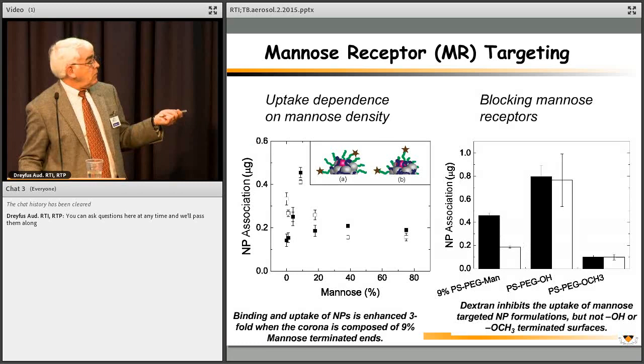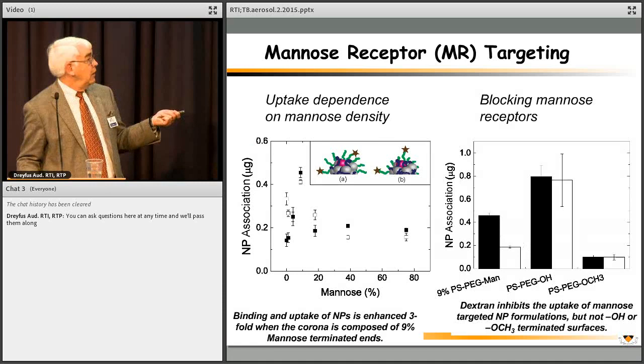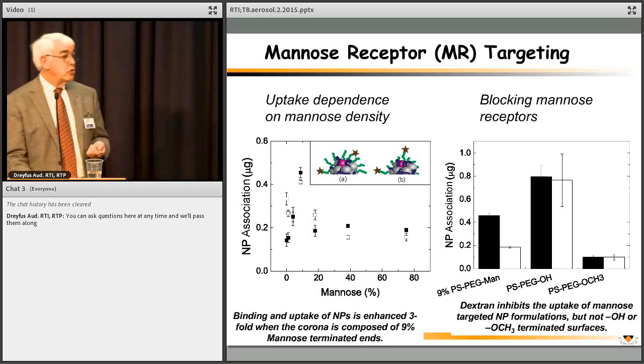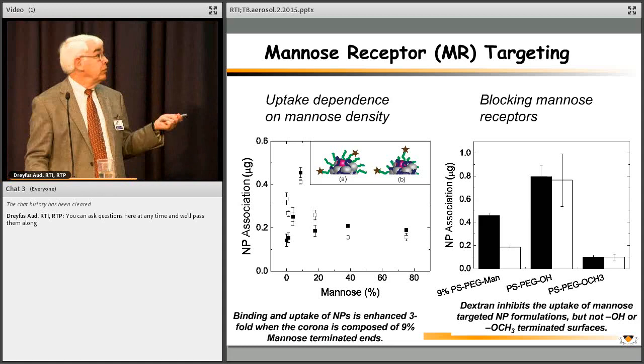You can show that it is mannose regulated. So this is the uptake for the methoxy terminated. You add a sugar to it, in this case dextran, and you block those mannose receptors and you decrease the uptake. These are the OH terminated ones. Adding dextran doesn't stop that. So the internalization mechanism for the OH terminated PEGs is a different mechanism. It's not apparently a mannose receptor mediated uptake, but it's a really efficient uptake mechanism for these particular macrophages.